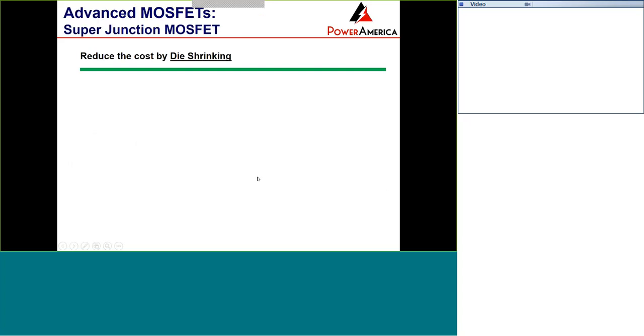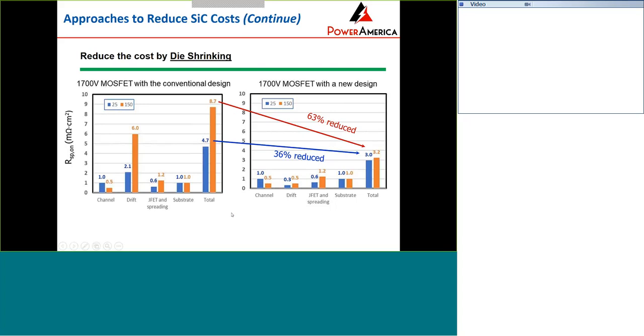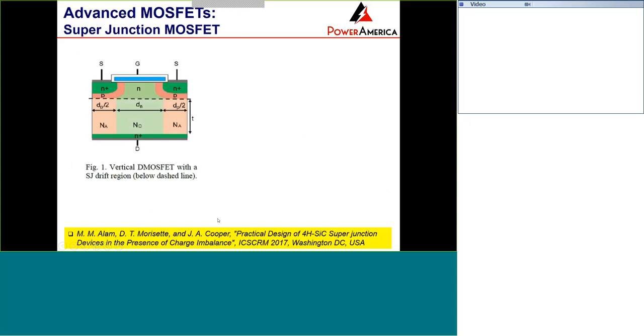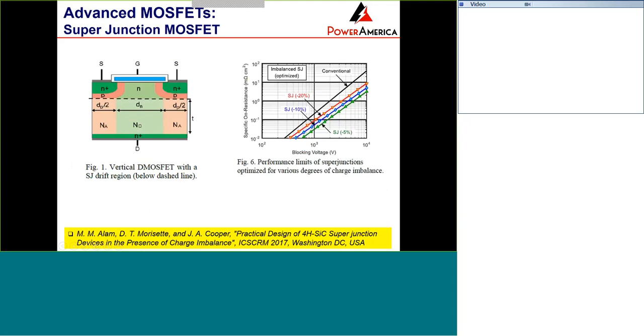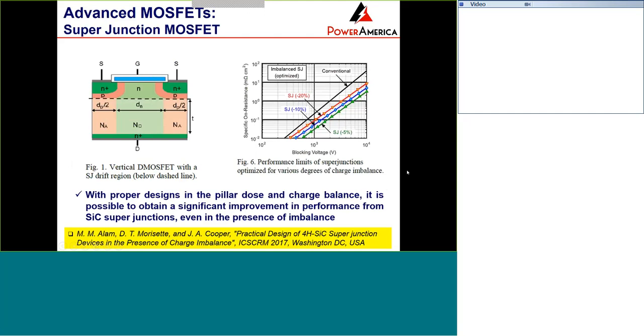So that approach looks very promising for high power silicon carbide devices in the future. Professor Cooper's group has done some simulations on MOSFETs with superjunction, as shown on the left side. That figure shows a very simplified superjunction with N-pillar and P-pillar structures. His simulation shows that if you design the pillar charge and spacing width properly, you could significantly reduce the drift resistance on silicon carbide devices. So it shows at least a future development direction to reduce the total resistance.